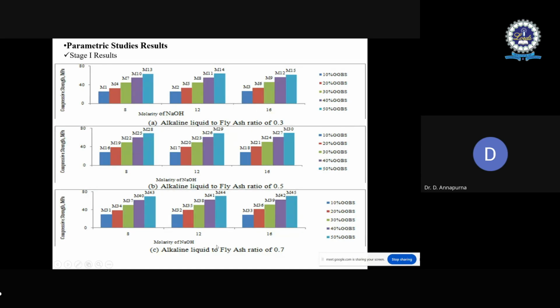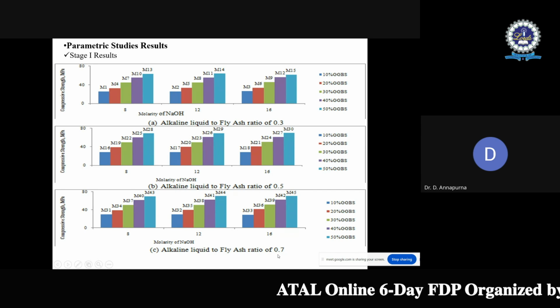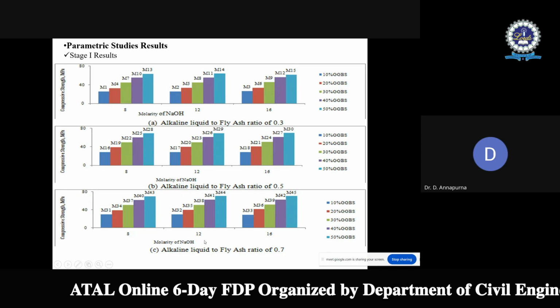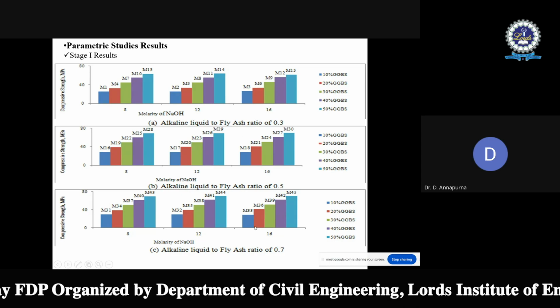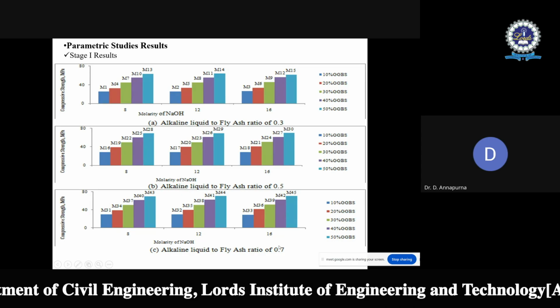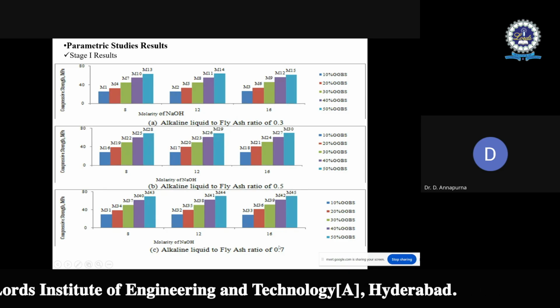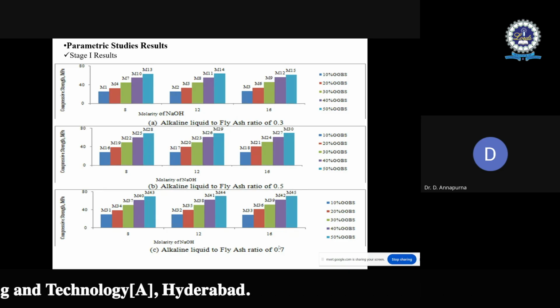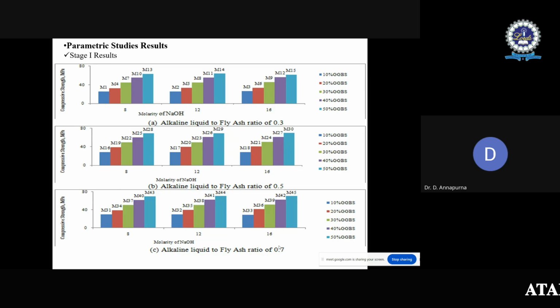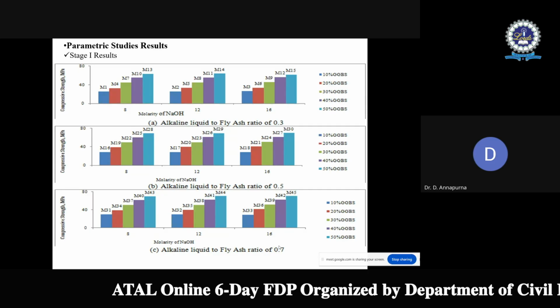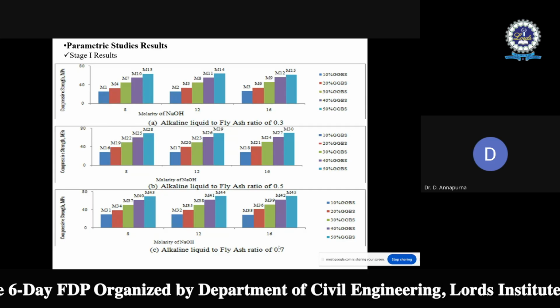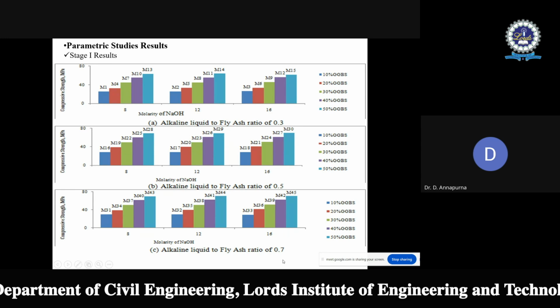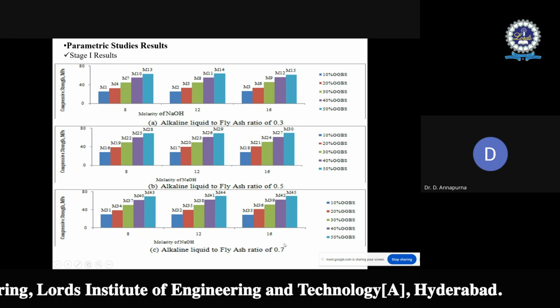And when we check the alkaline liquid to fly ash ratio of 0.7 mix, this mix consists of more alkaline liquid compared with the other two. If we see the nature of alkaline liquid, it is too cohesive, right? So the mix had better workability, but it is very difficult to handle the mix because of this higher amount of alkaline liquid. So keeping that in view, this alkaline liquid to fly ash ratio was not considered as 0.7.